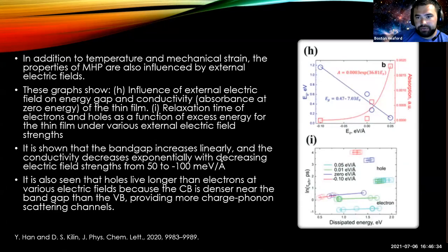So in addition to temperature and mechanical strain, the properties of perovskites are also influenced by external electric fields. And so these graphs show an influence of an external electric field on the energy gap and conductivity of a thin film. And also the relaxation time of electrons and holes as a function of excess energy for the thin film under different external electric field strengths.